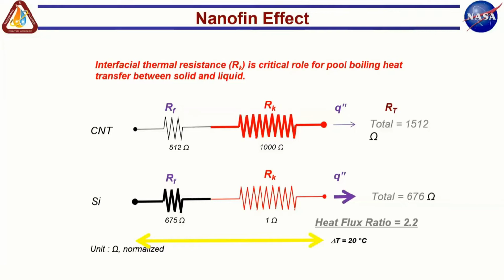On the other hand, if you look at the numbers for silicon, the fin resistance is 675, let's say about 700. The Kapitza resistance is only 1 ohm. And so your net resistance for silicon is actually half that for carbon. So it's not the fin resistance that dominates the game. It's the Kapitza resistance, the interfacial thermal resistance that dominates the game. And what we find is that the critical heat flux ratio also comes out to be a factor of 2 between the two cases.